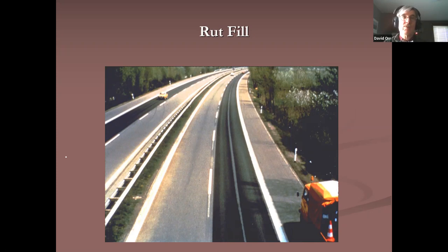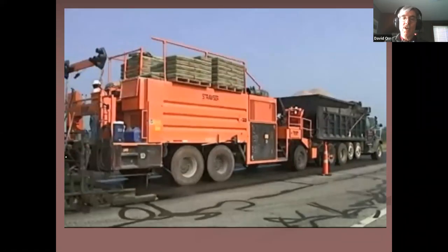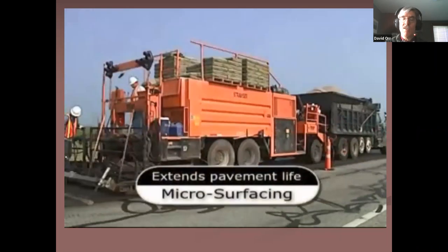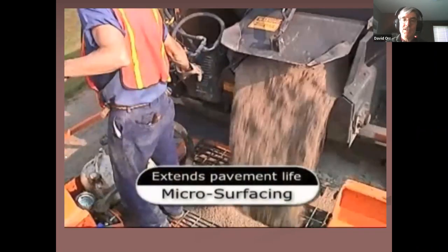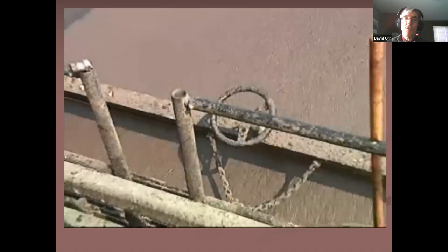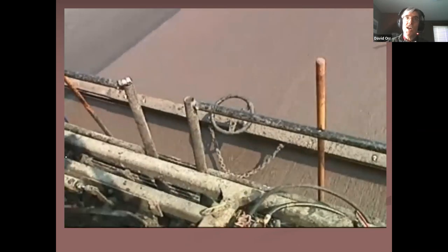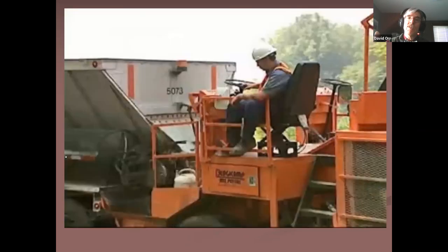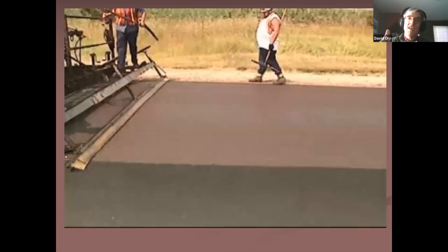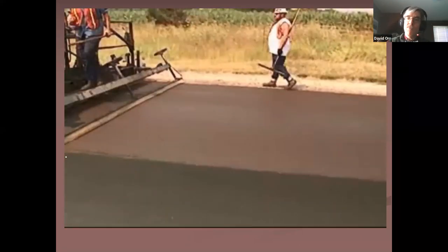And we're gonna take our risk. We'll see if our video plays here. I know there's no sound because I turned the sound off on this one. So this is a longer video from the International Slurry Surfacing Association. But what I want you to really watch is look at the color. The color in the back end of any of these slurries or micro paving or anything like that should be brown, okay? Much in the same way as a chip seal or a sand seal, I want to get the stones on it while it's still brown. The slurry should be brown when it's coming back out.